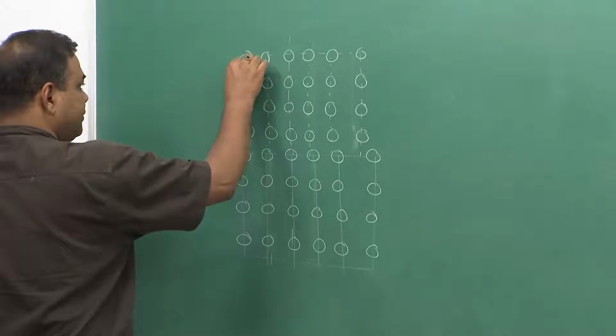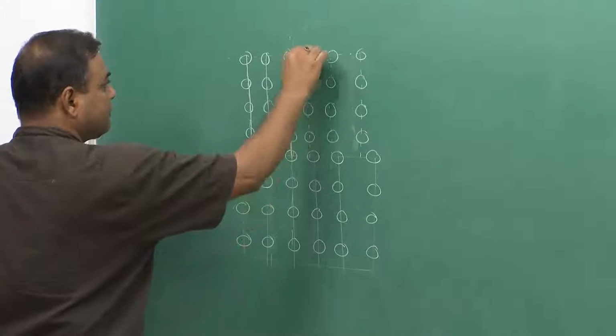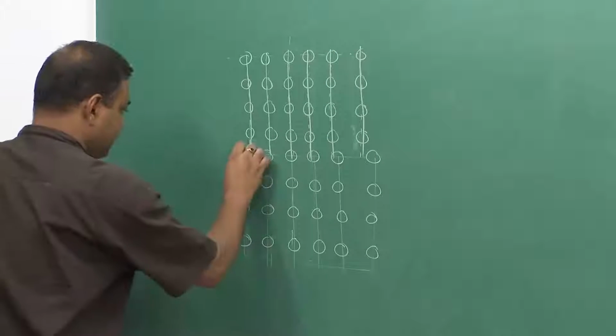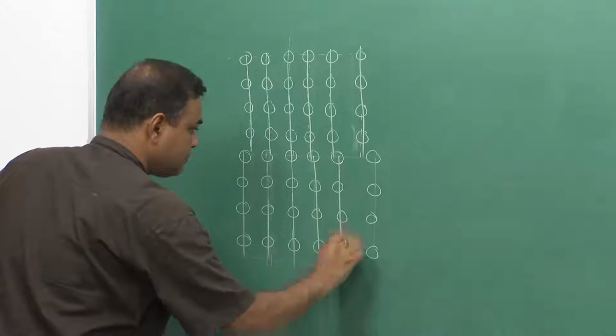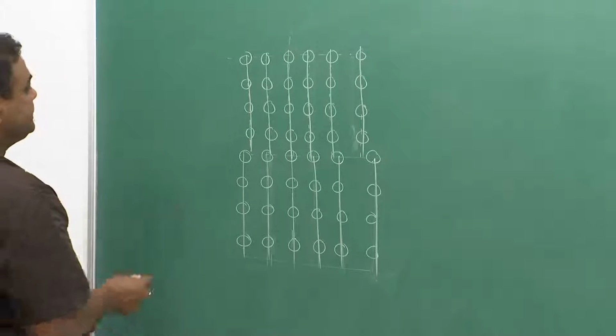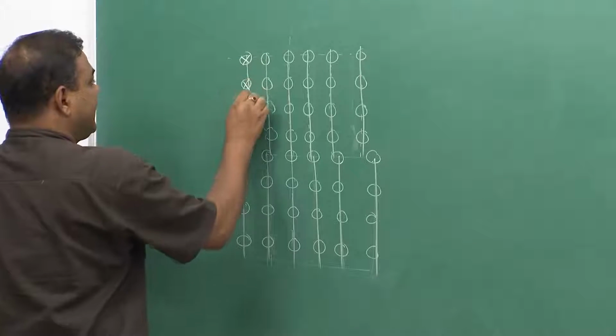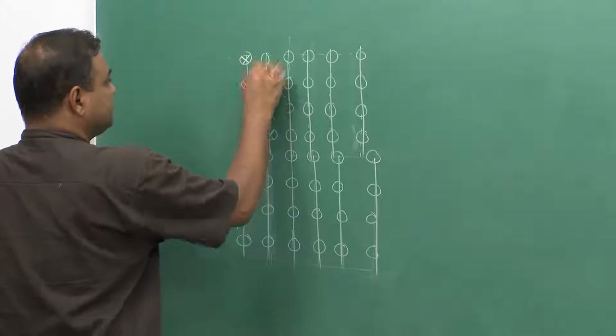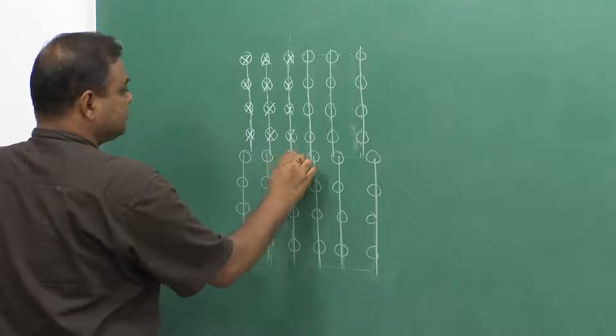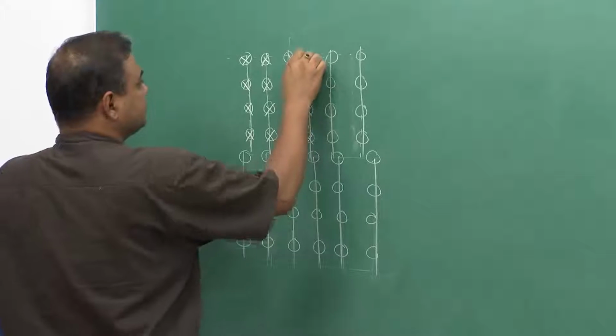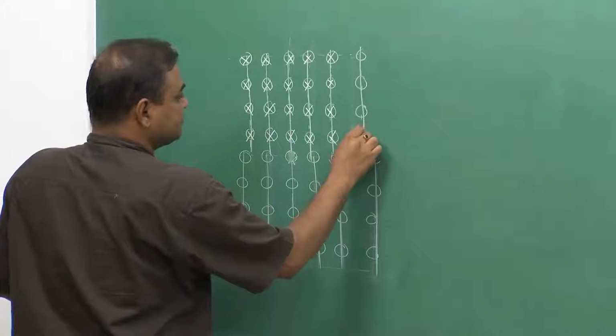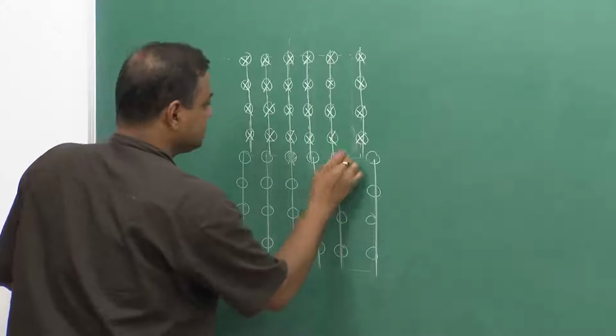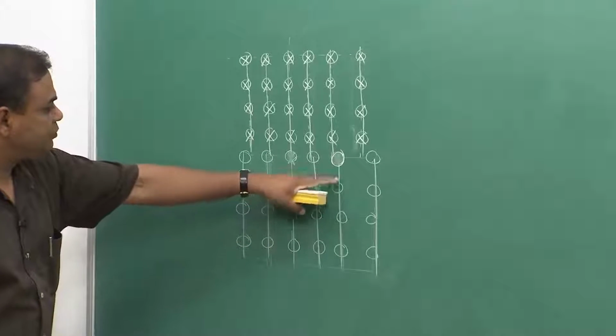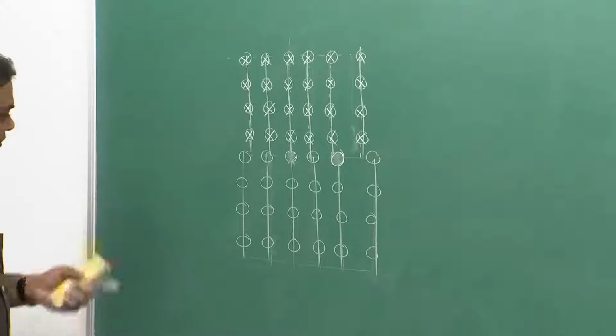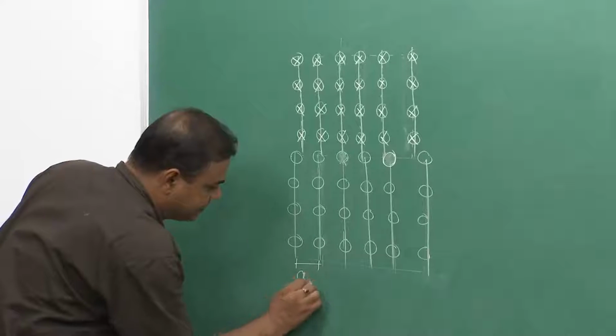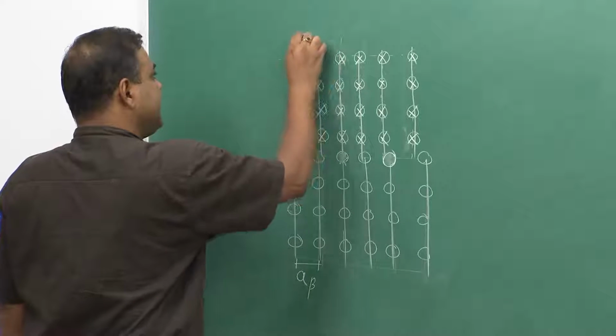If we see this particular arrangement, now these are, let us say, alpha atoms, and these open circles are beta atoms. There is an interesting thing. If we see this, this is, let us say, A beta, which is the lattice parameter, and this is the A alpha lattice parameter.